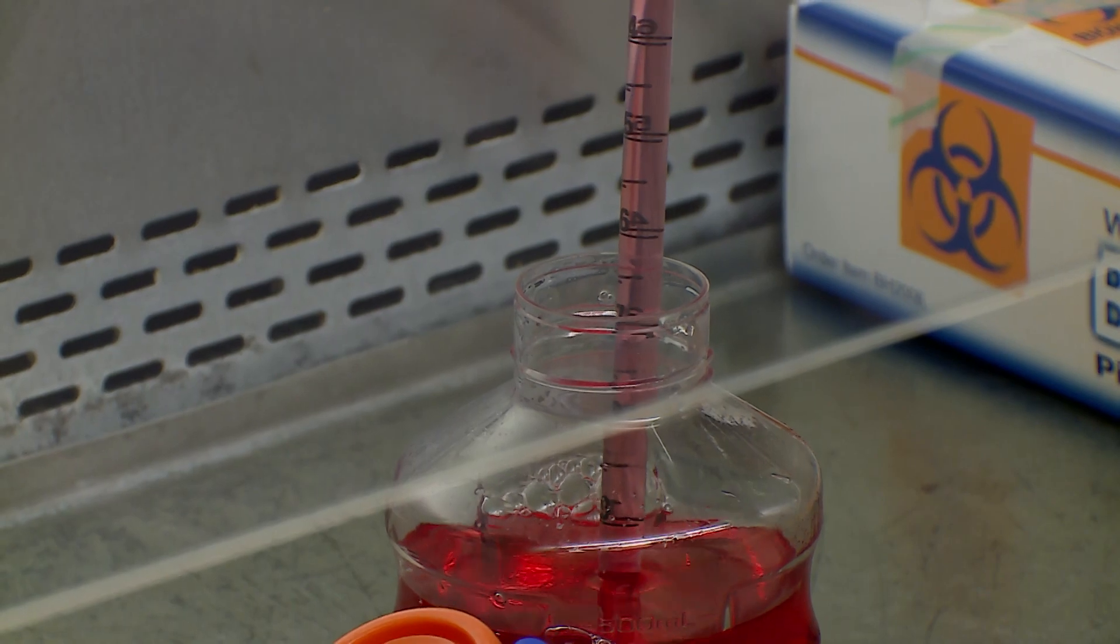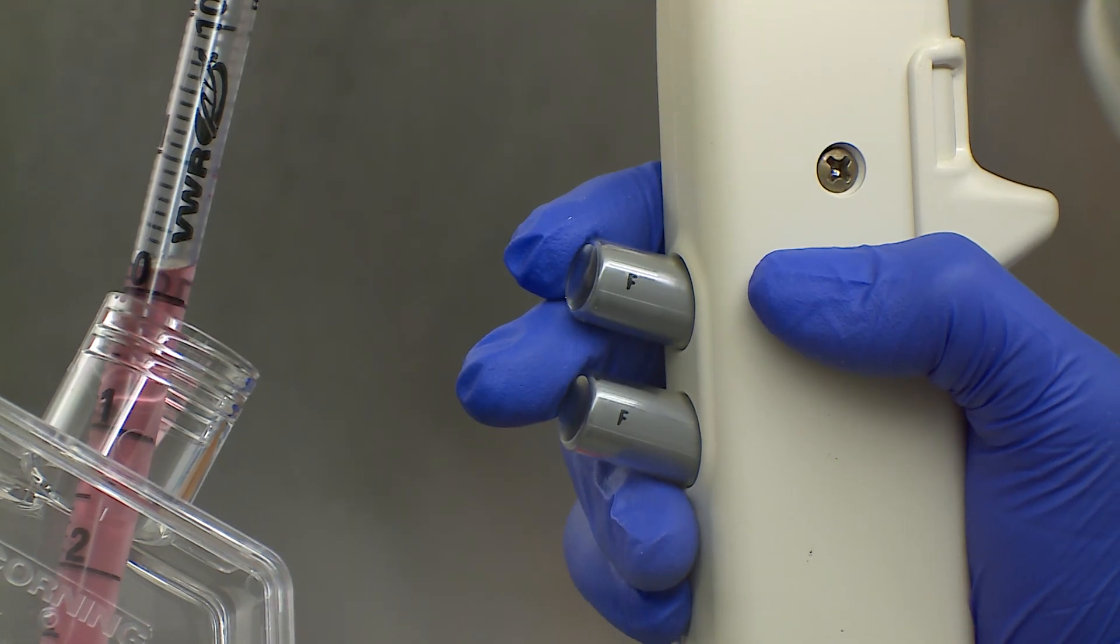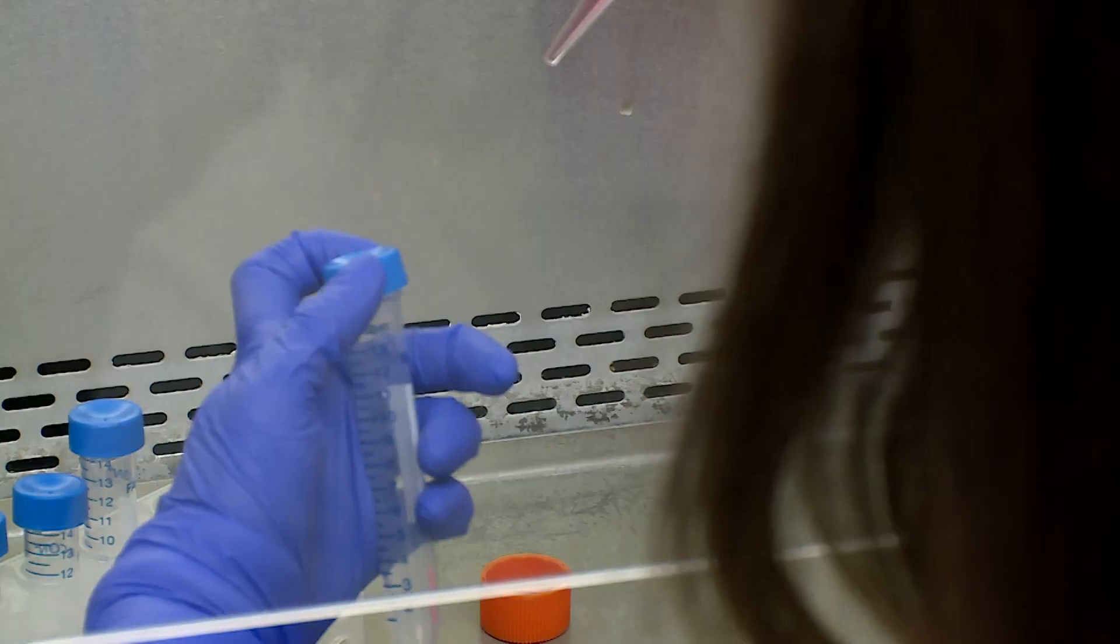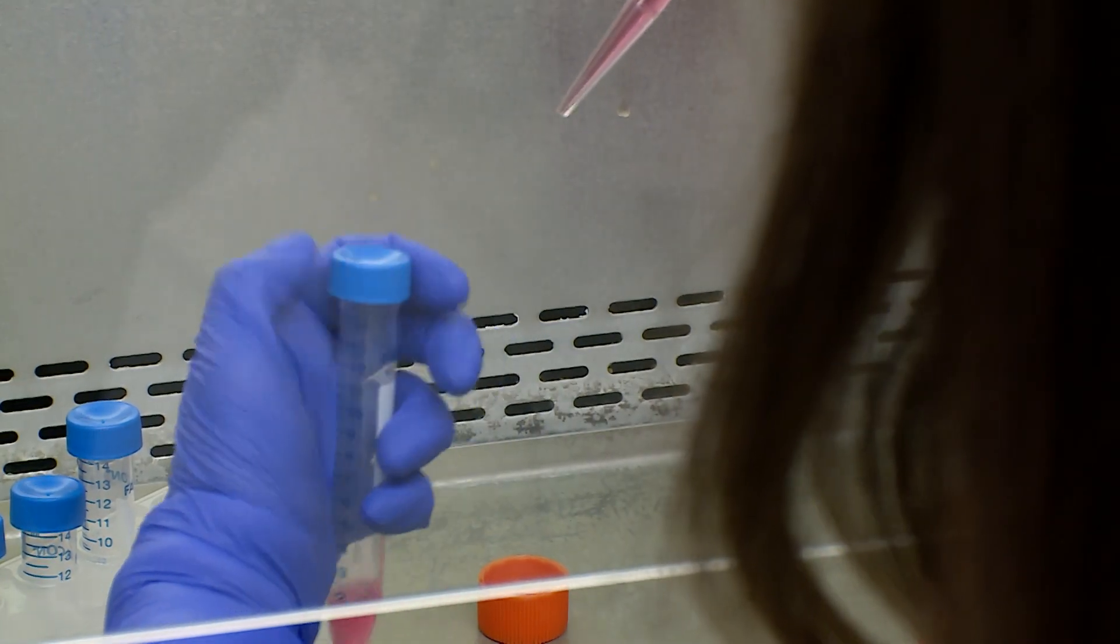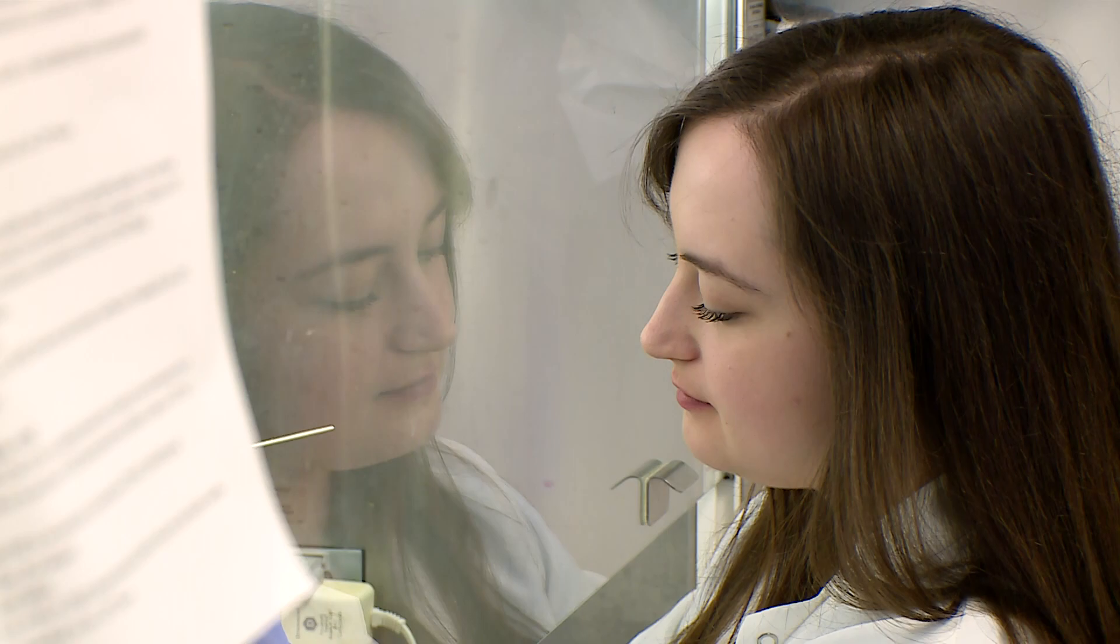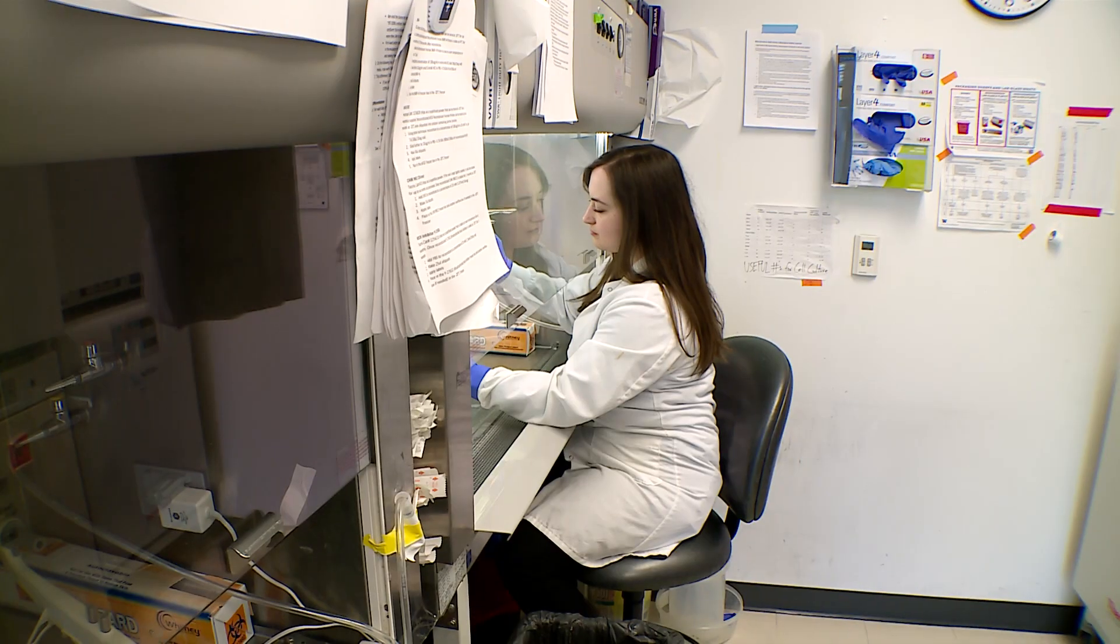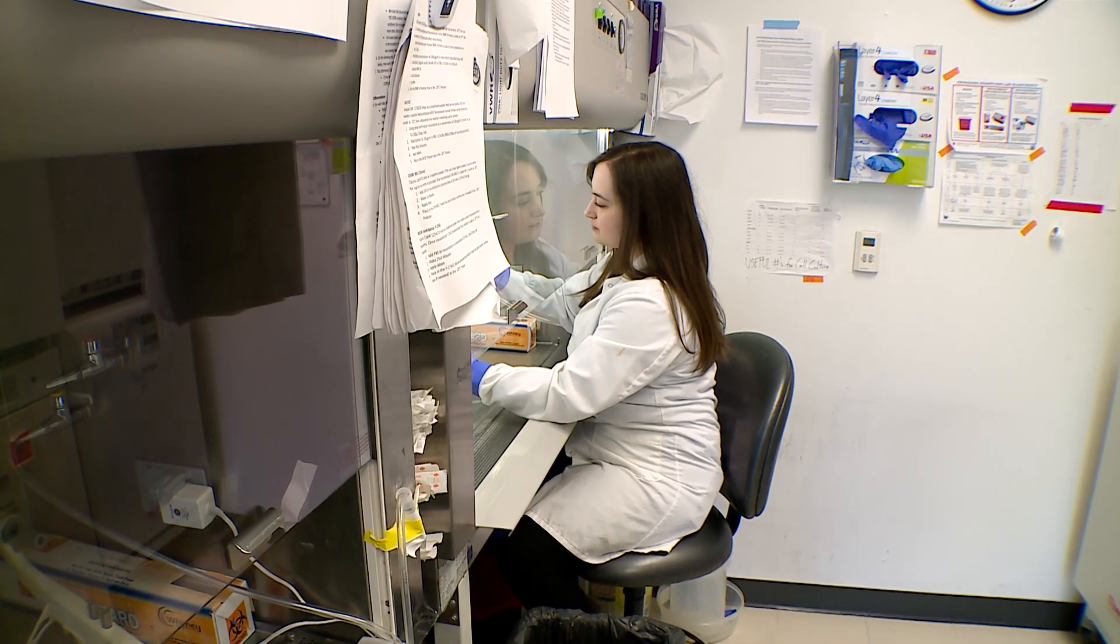In some of the other studies that we've done, where my lab has played the most central role, we actually embed living cells into the structures as we print them. We've been able to do that with liver cells called hepatocytes, and we've been able to show that they survive that printing process and that they retain at least one of liver's 500 functions.